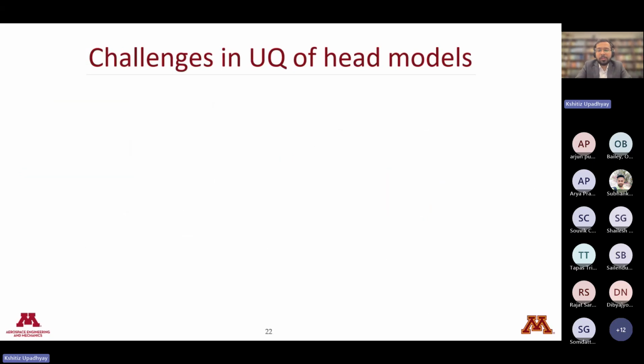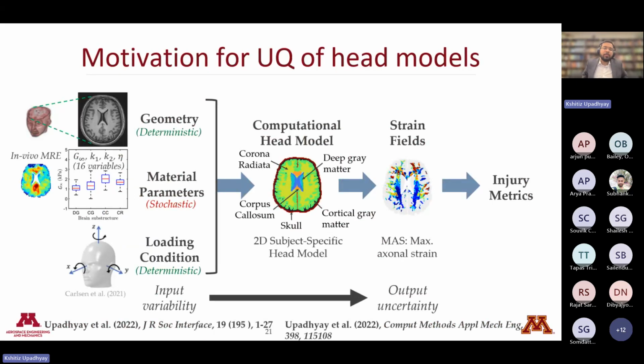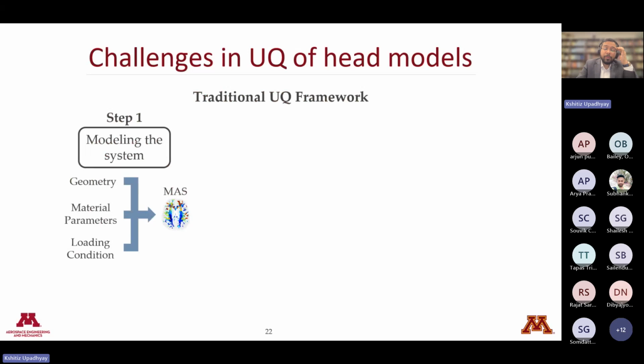Now let's look at what the challenges in uncertainty quantification are. The reason I had to develop a data-driven uncertainty quantification framework is because traditional Monte Carlo type uncertainty quantification was inadequate for this problem. So let's look at what the traditional UQ actually is. In a traditional UQ framework, there are 3 steps. The first step is modeling the system. I already showed you before, we have a 16-dimensional input, 16 sets of material parameters, and we have an output of 2,700 dimensions. So these are 2,700 data points. Each point can have a different strain value.